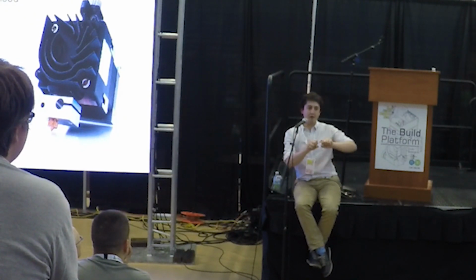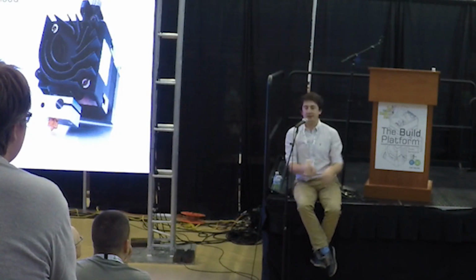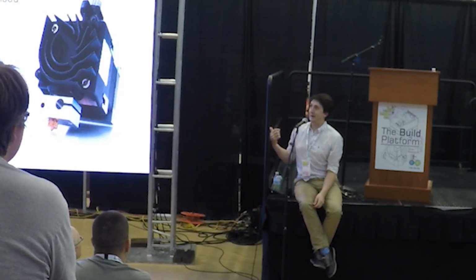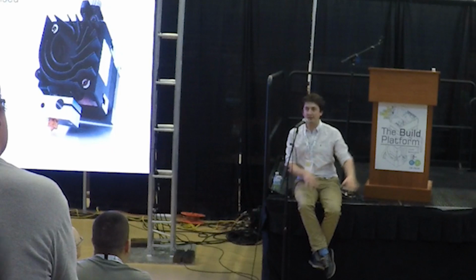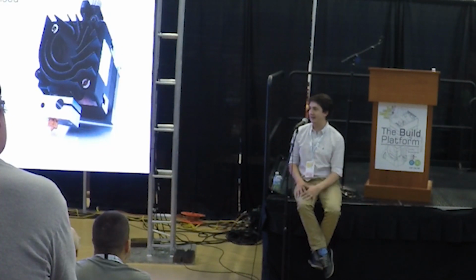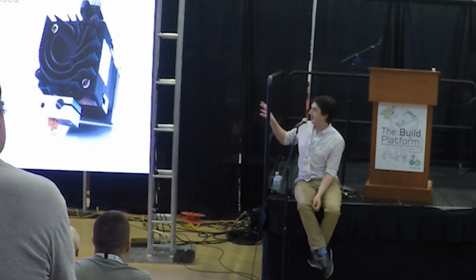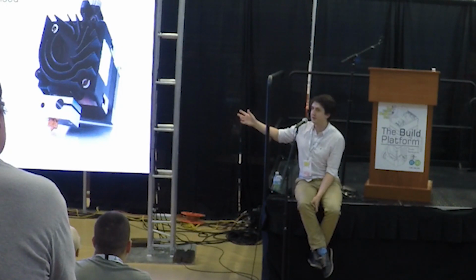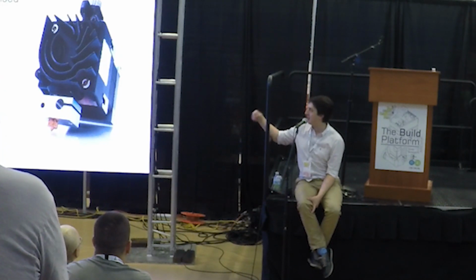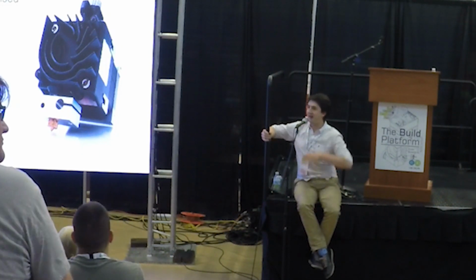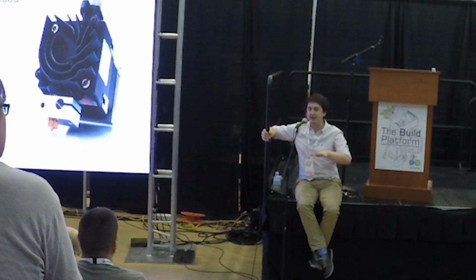Same deal with Aero. You get like a bit of dirty air on either side. Whereas the cool map for Hermes is dead flat. Really, really nice. Completely dead flat. So you can run even quite a powerful fan. But even with a very powerful fan, you will not disturb the air down in the print volume.